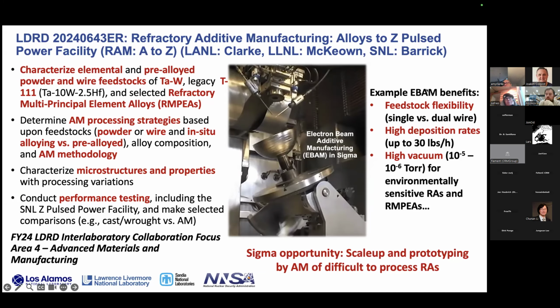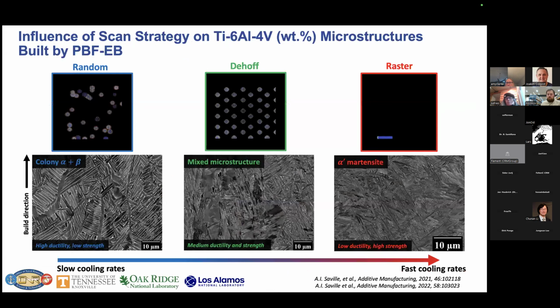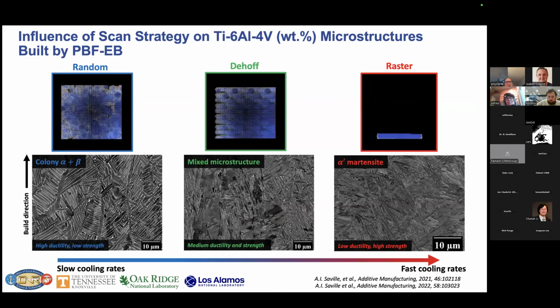Some neat advantages of EBAM or electron beam additive are, again, feedstock flexibility, the high deposition rates that we can have to make larger parts as well. And then the very important one for refractory alloys is high vacuum, especially important for these environmentally sensitive refractory alloys and refractory multi-principal element alloys. So switching gears a little bit, I'll talk about titanium.